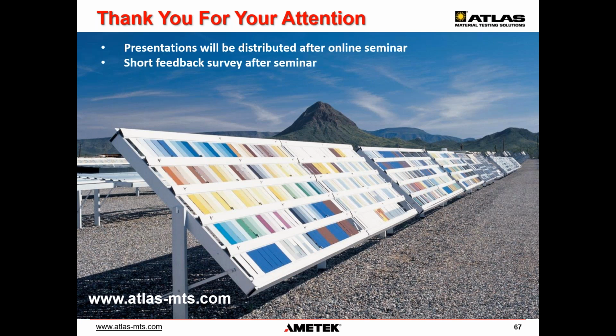The UVA 351 lamp has not really succeeded. It is a good lamp, but most tests are done with solar radiation outdoor simulation, but only in the lower wavelength UV radiation. Here, no visible and no infrared. It's still fluorescent UV, but this is the difference. So if you are looking at outdoor conditions, you have to use a UVA 340. If you are looking at behind window glass, you have to use the UVA 351 fluorescent lamps.